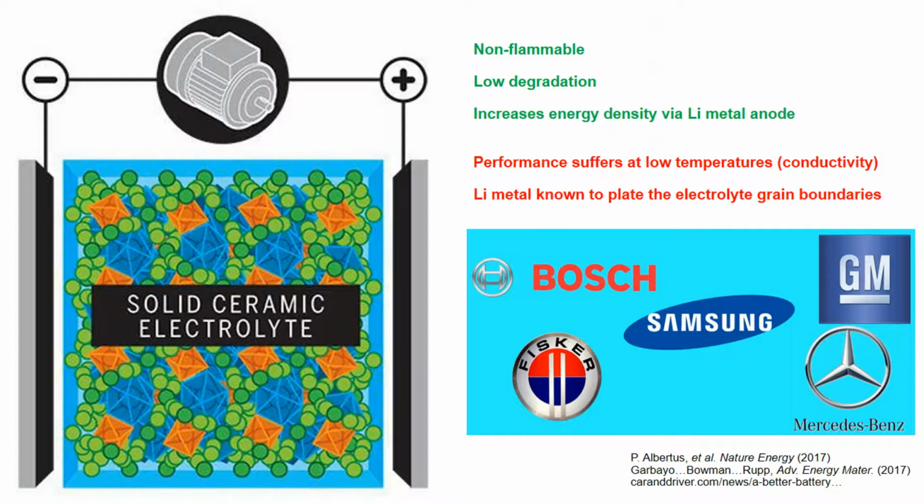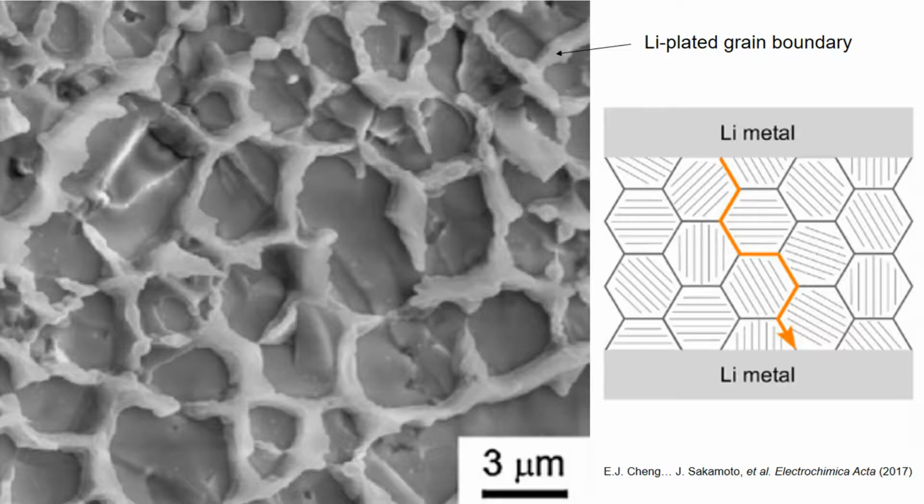Solid electrolytes enable higher theoretical energy density due to their chemical stability against lithium metal. These batteries are not without flaws, however. Because the electrolytes are solids, lithium-ion conductivity drops with temperature, thanks in part to highly resistive grain boundaries, which degrade ion transport in many similar solid electrolytes. Grain boundaries can also become plated with lithium metal during battery operation, causing batteries to fail by short circuit.